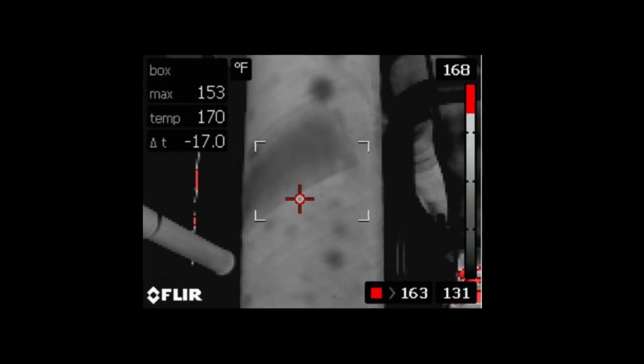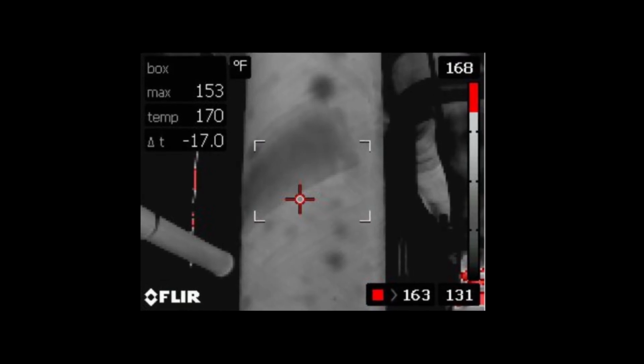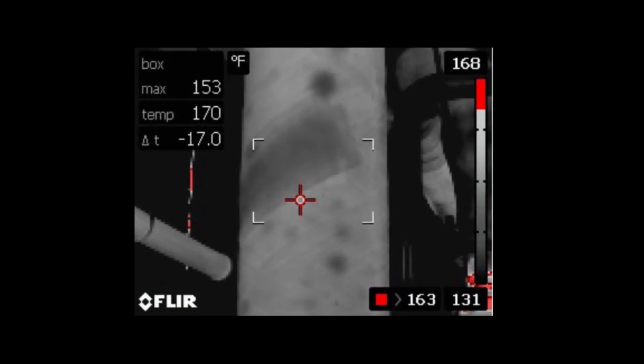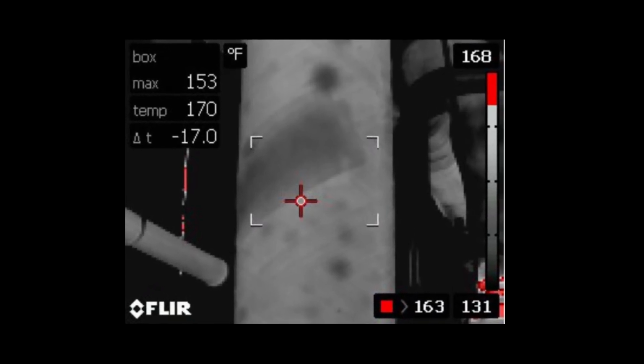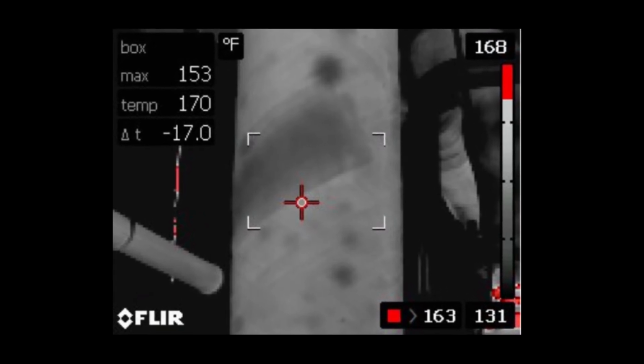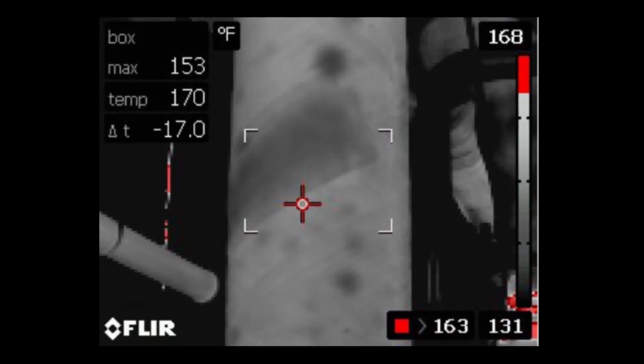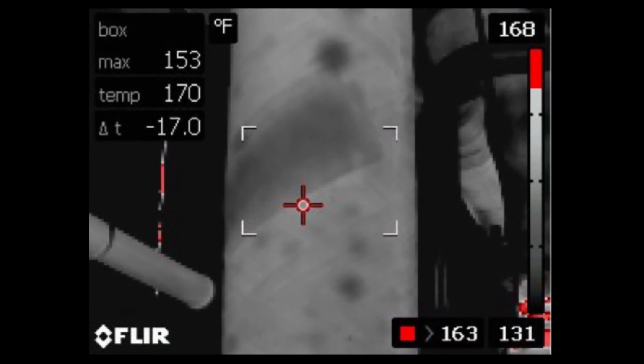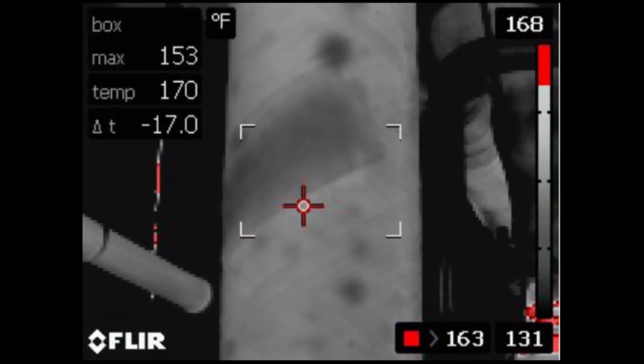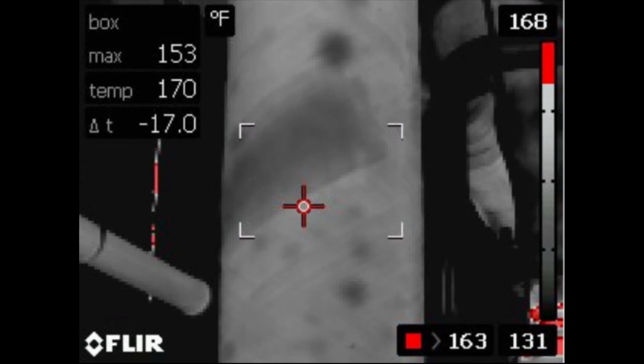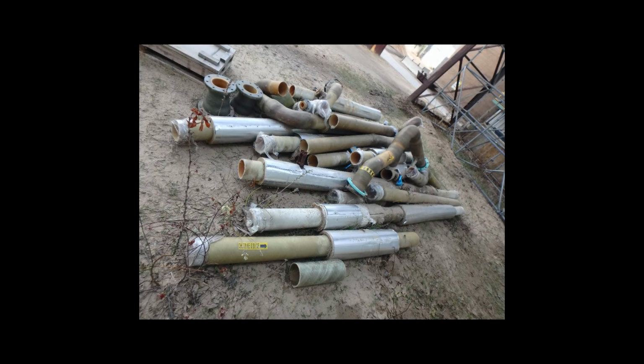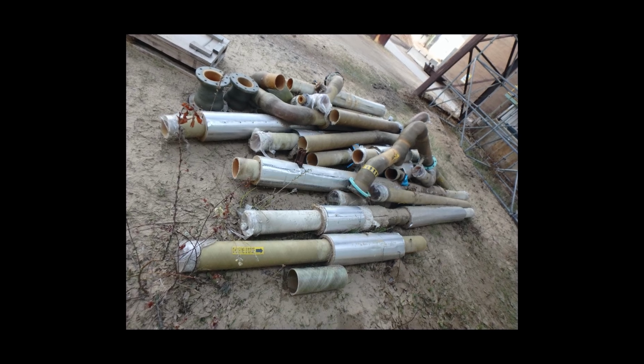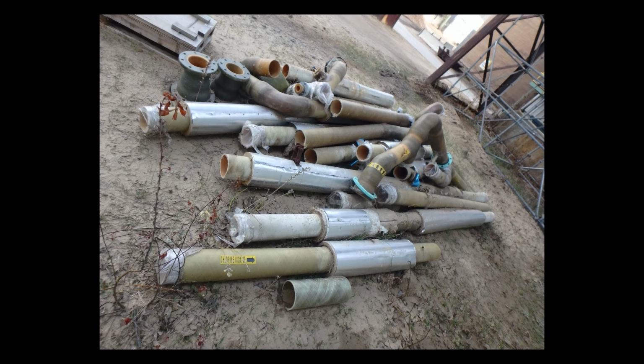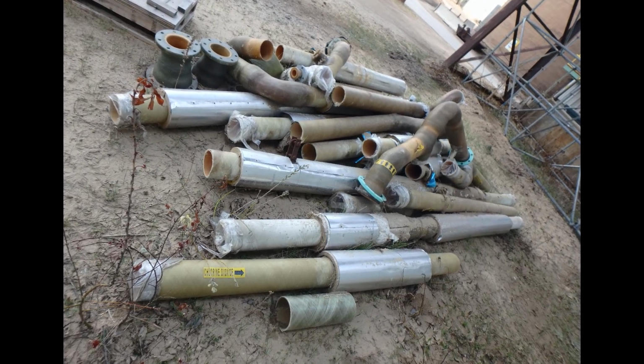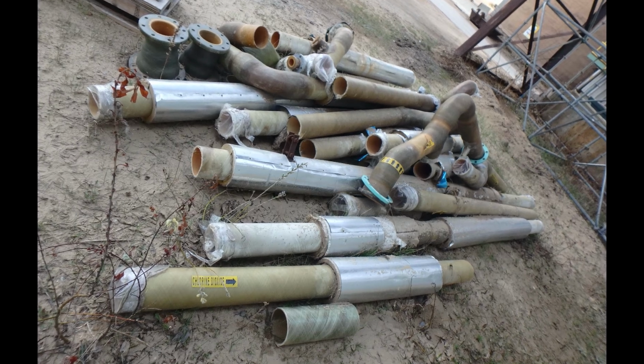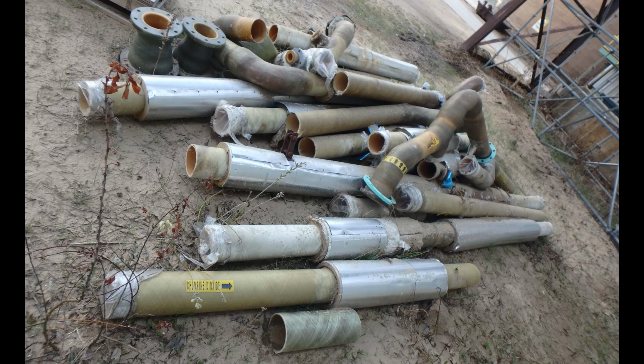For example, mid-wall embedded delamination is reasonably easy to detect with UT and X-ray and even thermal methods. The problem is, delamination has some effect on localized flexural strength properties, but less on tensile strength or the beam stiffness of the structure as a whole, and is therefore seldom a valid reason to recommend action unless delam is close enough to the surface to cause disruption and the total wall is marginal overall. Delamination has resulted in millions of dollars of FRP equipment replacement, yet it is usually the result of poorly bonded past repairs or manufacturing problems that have existed since the equipment was new. We needed a solution that quantifies the laminate degradation that truly threatens the reliability of the equipment.